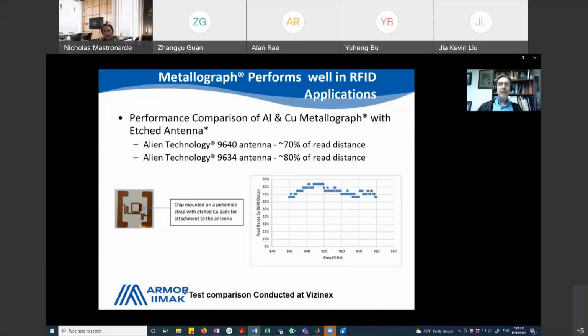We hypothesized that the low resistance and high uniformity of the metal deposition really contributes to this good performance. Later in the talk, we'll discuss how matching the impedance of the thermally printed antennae and the RFID chips has really eliminated the read distance gap, providing equivalent tag performance to the etched metal antennae. Let's first focus on the sustainability advantages of thermal transfer printing.